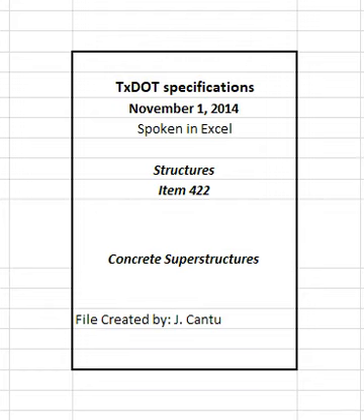Provide burlap material which complies with AASHTO M182, Class 3, 10 ounces per square yard, with the following additions. Manila hemp may also be used to make burlap. Do not use burlap fabricated from bags. Do not use burlap containing any water-soluble ingredient which will retard the setting time of concrete. Provide used burlap complying with the requirements stated above, and that only has been used previously for curing concrete. Like new cleanliness is not expected, but contamination with any substance foreign to the concrete curing process, such as grease or oil, will be cause for rejection.